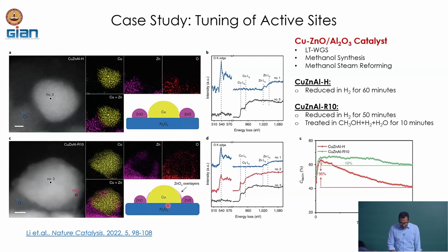So, if we look at these two catalysts, how these two different treatments are reflected on the catalytic activity, we see that the initial activity is not very different. However, if we put the catalyst for long hours in the reaction environment, which is for 40 hours, we see that the catalyst which was treated just in hydrogen is deactivating over time, and a 35% loss of the initial activity has been observed for 40 hours on time. The other one is decreasing only by 10% as compared to the 35%.